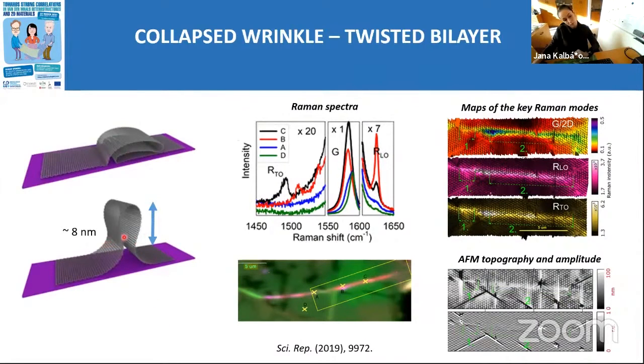Nevertheless, if we look from the side at that wrinkle, we can say, well, it's simply the same as if we had a bilayer, a twisted bilayer. And if we inspected these samples in more detail with our probes, I'm not going to describe the AFM imaging here, I will go directly to the Raman. So here is a scan along such a collapsed wrinkle, as we can call it. And there are areas where we see, first, extreme enhancement. This always suggests that there should be some kind of resonance with the laser, which will tell us roughly what the mutual orientation of the layers is. And second, we observe here some extra bands.